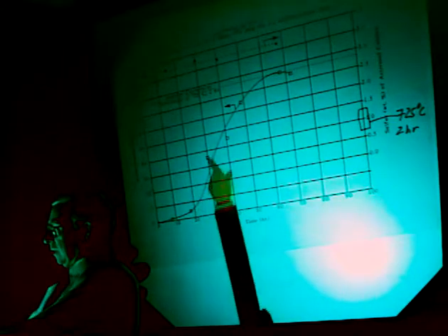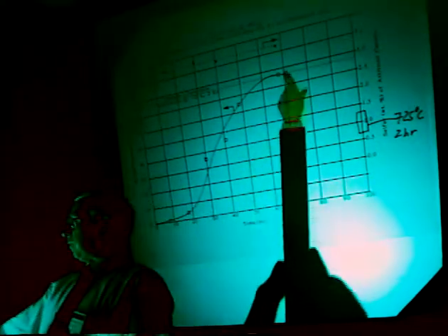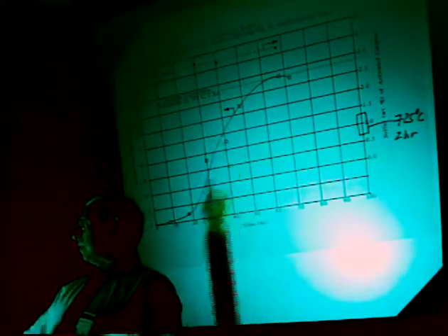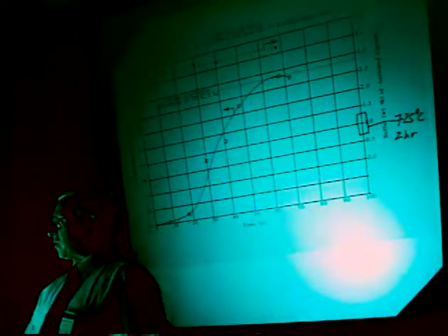If, on the other hand, we activate at a lower temperature, 500 degrees centigrade, you start out, gradually gain activity, eventually attain roughly the same activity as if you had done it at higher temperature, shorter time period. The major difference is that you do not lose sulfur at the lower activation, but not all of this sulfur is contributing to the activity.